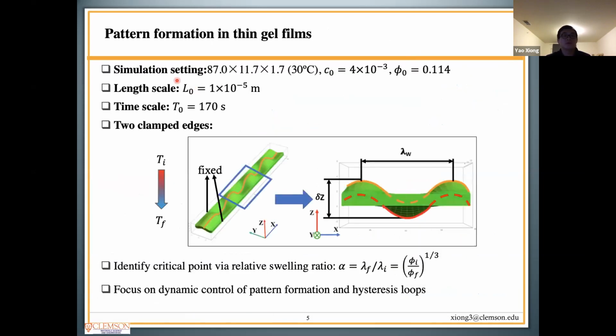Here are the set-ups and the scales in our simulation. Gels initially are flat and equilibrated at a relatively higher temperature. After fixing the two edges, we quench down the temperature of the hydrogel to a relatively lower value. We characterize patterns by the amplitude and the wavelength.